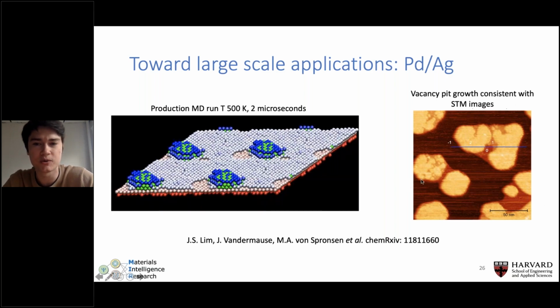And we can compare it to experiments. So this is STM images coming out of Cynthia Friend's group at Harvard. Essentially the same system where palladium was deposited on top of silver, and they looked at what happened when you anneal it at various temperatures. And they saw essentially the same type of behavior where these large-scale vacancy pits start to form on the first layer of the material.